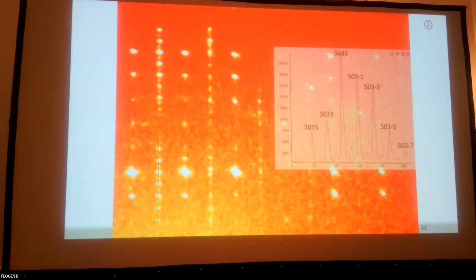And it is not in that sense a problem that the measurement conditions were not good enough. So it was measured at the synchrotron, so it was not that we were just doing that at a home source. So this is actually a problem where a different data evaluation strategy must be applied.